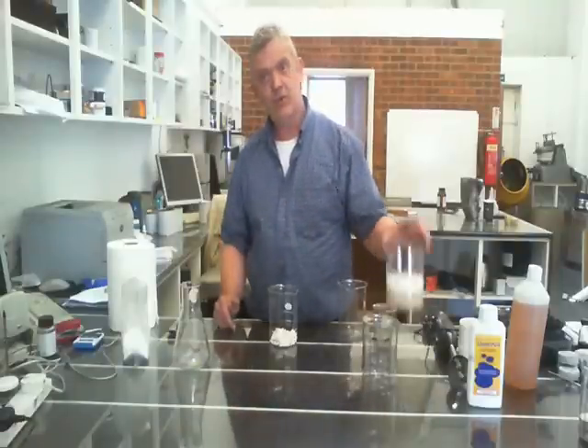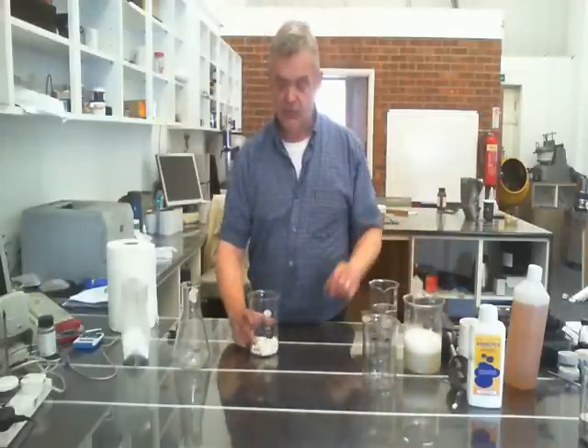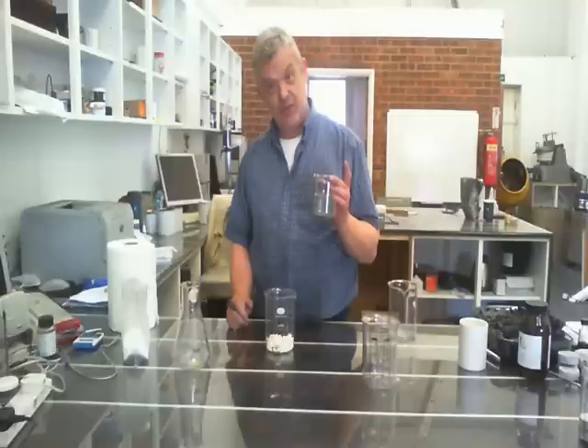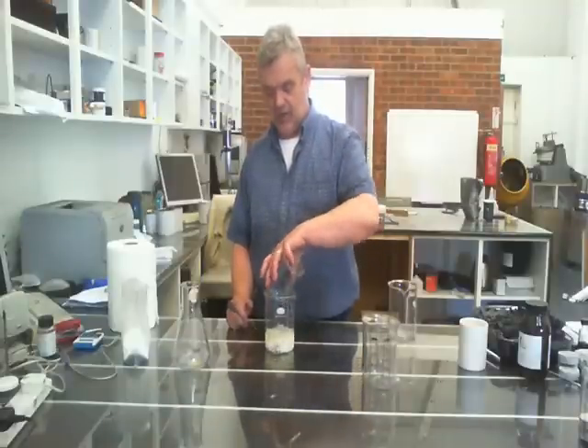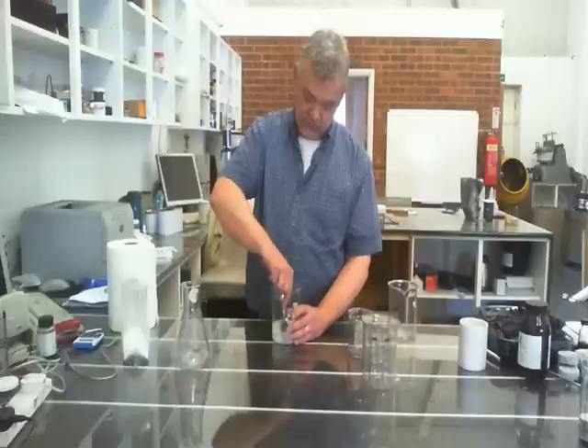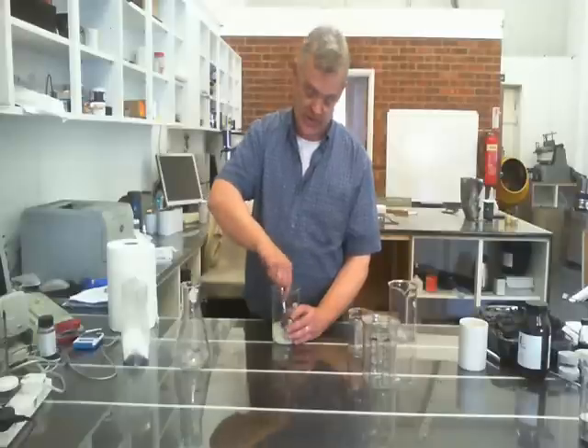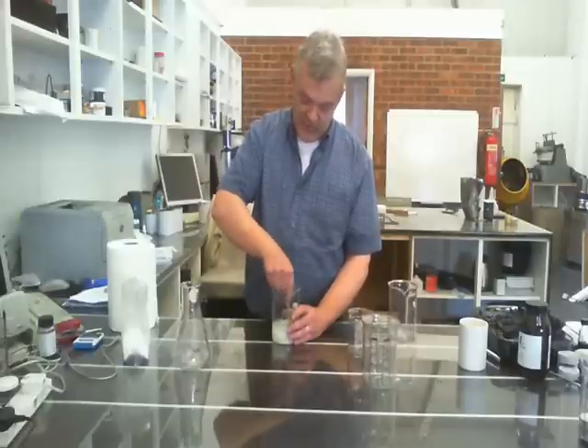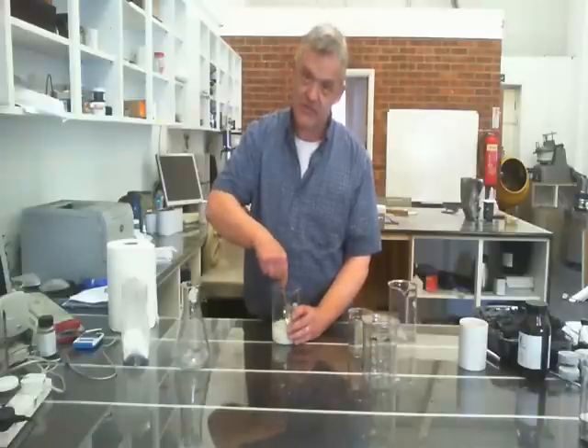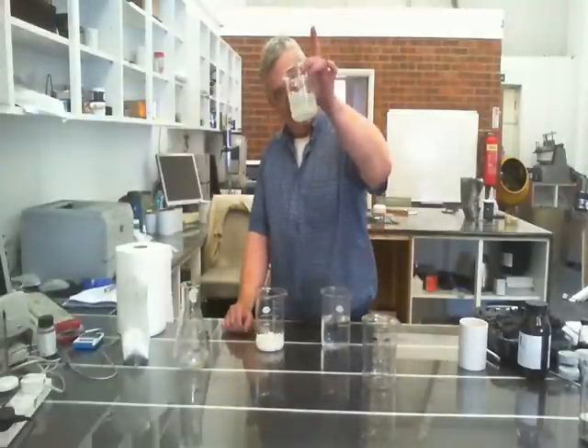There's another way to do this, and that's to use methanol — you can also use ethanol. Just pour the methanol onto your casein and swirl it around for about five minutes. That will dissolve out any remaining salts, help the fat particles separate, and clean the water out of the casein, so you get methanol-soaked casein instead of water-soaked casein — it's a solvent replacement. Give that a swirl for about five minutes and then pick out the cleaned casein. You can decant or filter off your methanol, and you can see how dirty it's gone — a yellowish color — because it's full of all the excess bits and pieces that were in there.